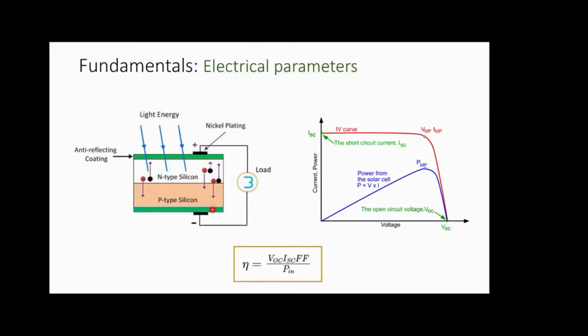We are talking about dielectric relaxation. That means how carriers travel through a layer having the majority carrier of the same type. Once your carriers are in these carrier collection layers, the lifetime is not important anymore because your carriers have become majority carriers. Am I answering the question?